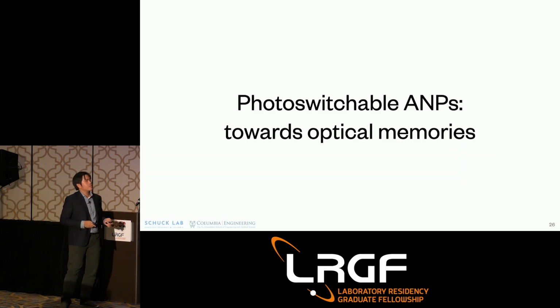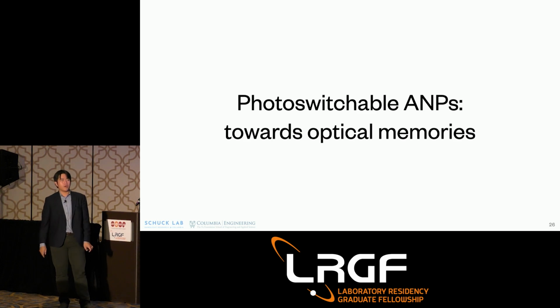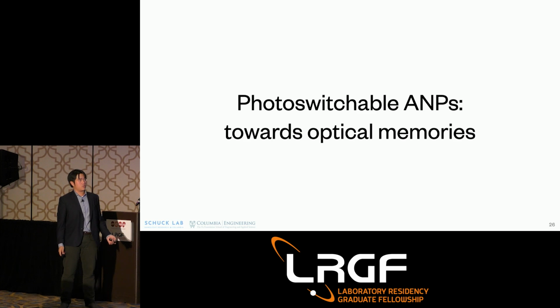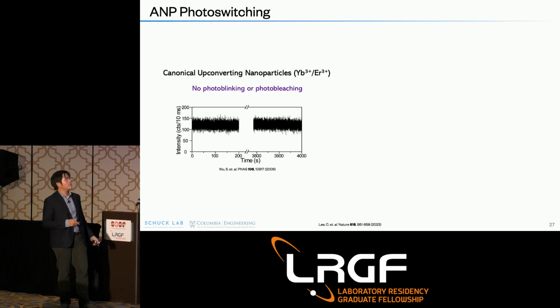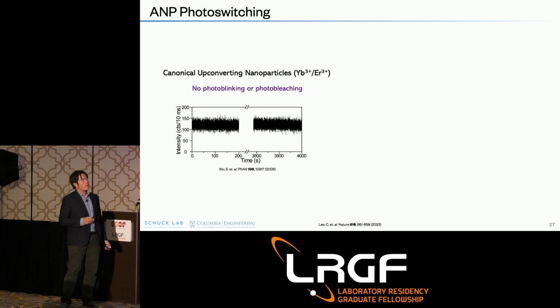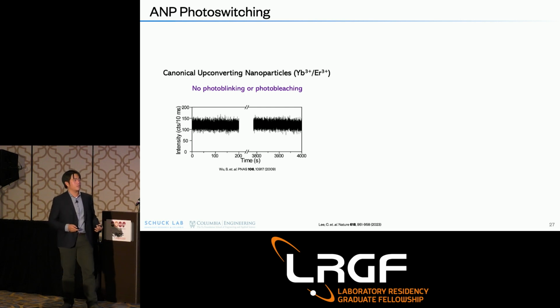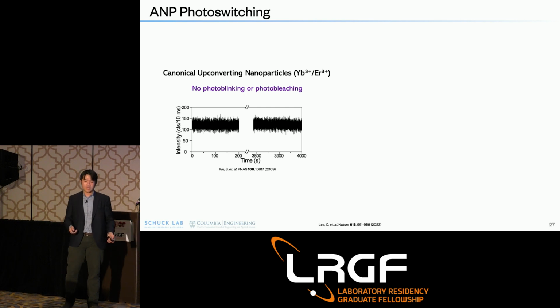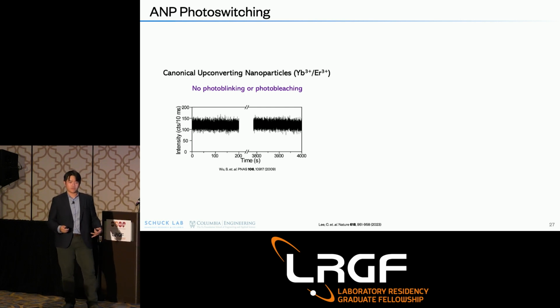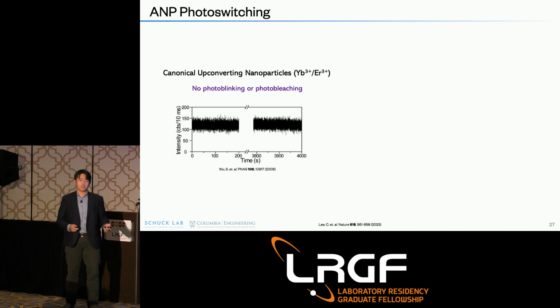Last but not least, one other project that I got involved with at school was to understand whether these ANPs can have other applications as well. One of the more interesting observations that we've seen was when you compare these to canonical upconverting nanoparticles, which are known for their photostability. They don't blink and they don't photobleach. Compared to other dyes that people use for bioimaging, which tend to bleach and degrade pretty rapidly, these nanoparticles do not.